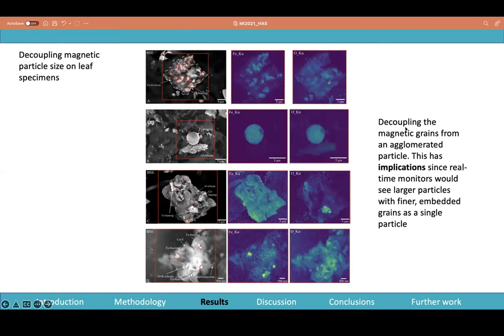These are some SEM results we got. And this is where you can see how there are certain Fe bearing particles which were embedded on top of a calcium aluminium silicate. You can see a very nice spherical looking magnetite particle, potentially magnetite. It has both iron and oxygen signals coming from it, sitting on top of an aluminium silicate. So this is what we are trying to focus on: when traditional PM monitors have a filter of PM2.5, if there are certain finer particles which are attached to these surfaces, they might go unnoticed in these traditional measurements.